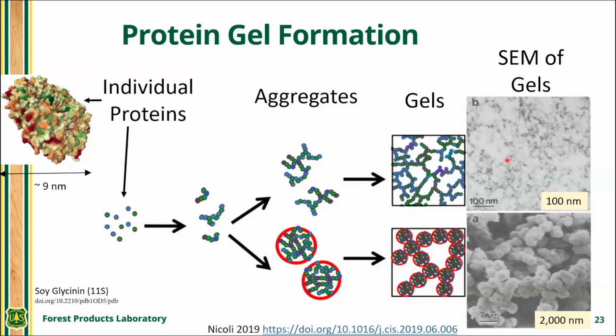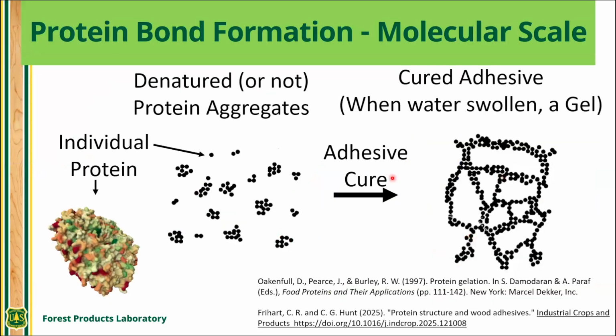So these are protein gels from food processing. And so we take that idea and we say, okay, now we're going to make an adhesive, denatured or not protein aggregates. This is how they come in, in the adhesive, and then we go through the cure and create a water swollen gel. Well, actually, it's not water swollen when it's cured. It's only water swollen when you're about to do the wet test.